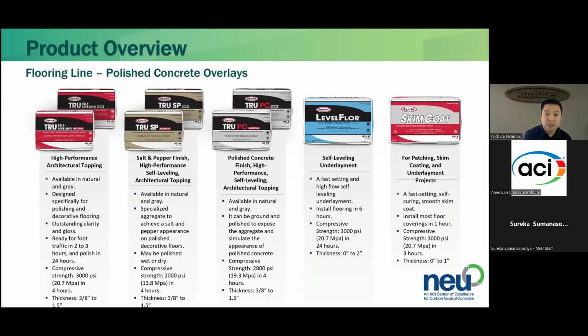And in a similar fashion to the previous slide, I can say that I've participated in the PCR committee for polished concrete systems. And while a lot of that has to do with the actual system of grinding and polishing existing concrete, there is language for using a topping and polishing that topping. Obviously, if you have to put in additional material, that's going to add financial and GWP costs to the project. So it's preferable to use existing concrete, but in cases where there's an engineering reason, an architectural reason, or simply a design and aesthetic reason why a topping should be placed, there's a solution for that. And we have, because it's powered by Rapid Set Cement, it's a lower embodied carbon material.